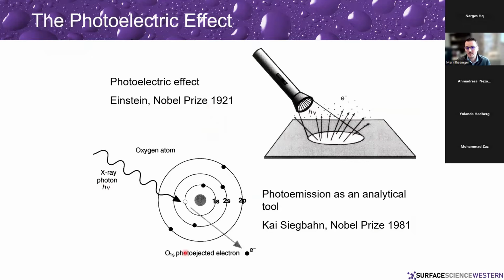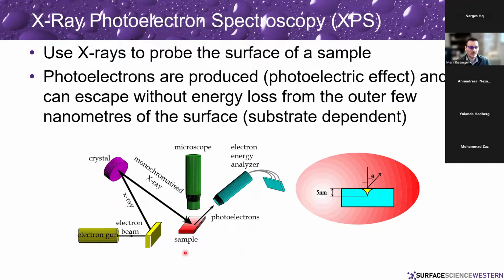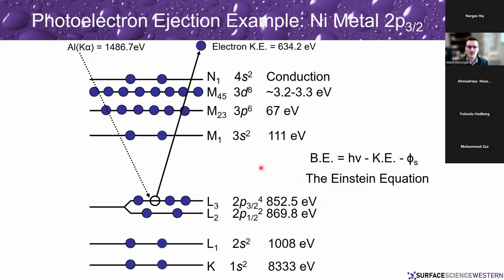XPS works on the photoelectric effect. Basically, shine X-rays at the surface, photoelectrons are ejected. To get X-rays, you use an electron gun, hit the surface of an anode, such as aluminum or magnesium, run that through a crystal monochromator down to your sample surface. Photoelectrons are produced, and you measure the kinetic energies of those photoelectrons. And those kinetic energies can be used to calculate the binding energy of those core electrons from the various atoms. So again, usually what we are using in this case is aluminum K alpha X-rays at 1486.7 eV.